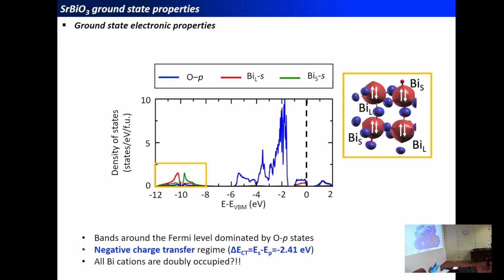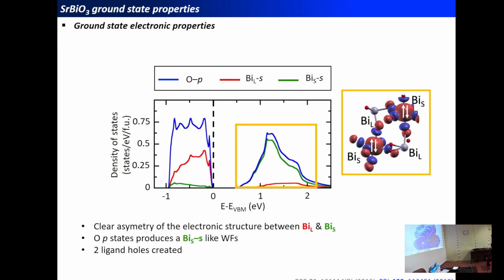Nevertheless, if we zoom around the Fermi level, what we see is the presence of an asymmetry of the bismuth S states around the Fermi level, with these small bismuth cations having partly unoccupied S orbitals, but also there are oxygen p states that are not occupied, meaning that the oxygen p states are not totally occupied in this material. And in fact, it comes from the negative charge transfer insulator regime, in which the oxygen p states are giving electrons to the bismuth cations.